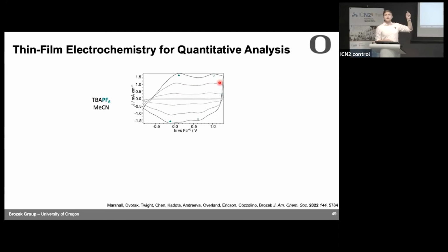And we realized that iron triazolate actually has pretty small pores for a MOF. You think about a MOF, the pore could be 1 nanometer, 2 nanometers, but in iron triazolate, it's only about 5 or 6 angstroms. And so we started to worry that maybe PF6 is actually too large to go into the pore. And so we started to think that maybe the less positive redox feature, the easier to oxidize iron, is iron that's on the surface. And maybe the reason you have these other redox waves at really positive potentials is because that's the additional energy that it takes to try to oxidize the iron sites that are on the inside.